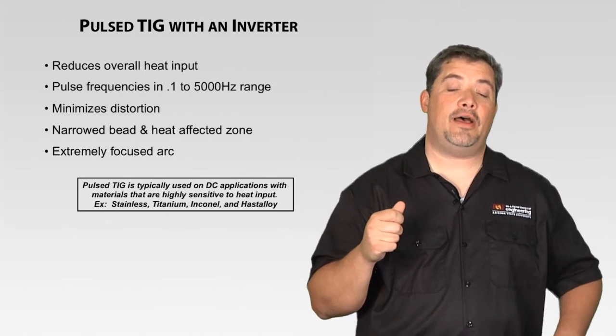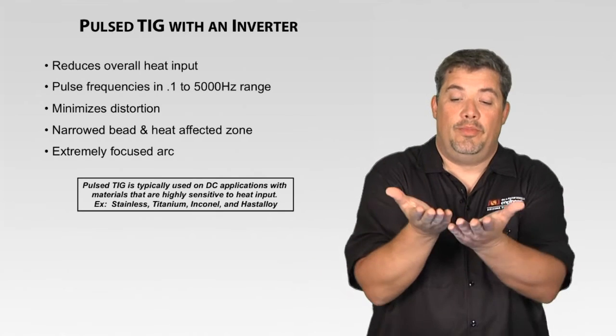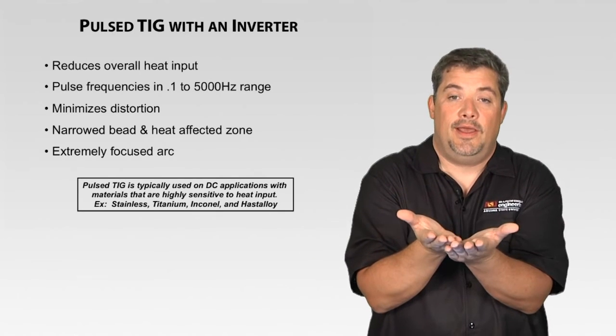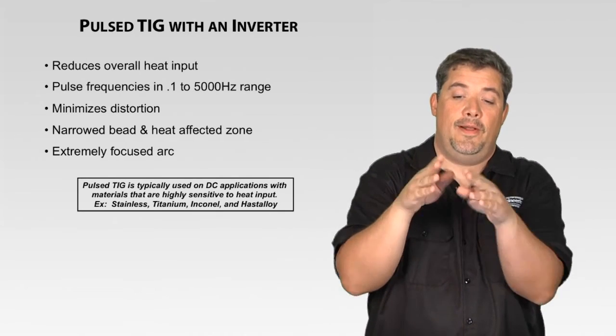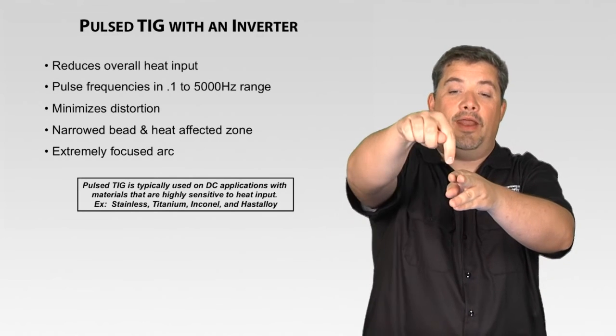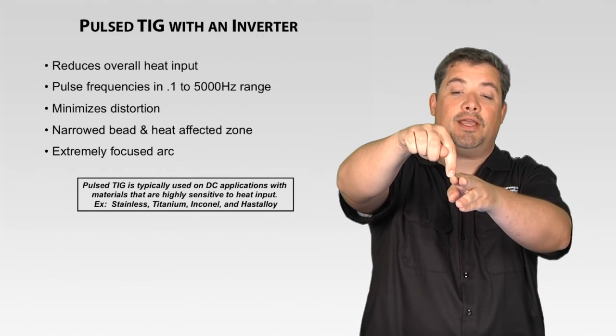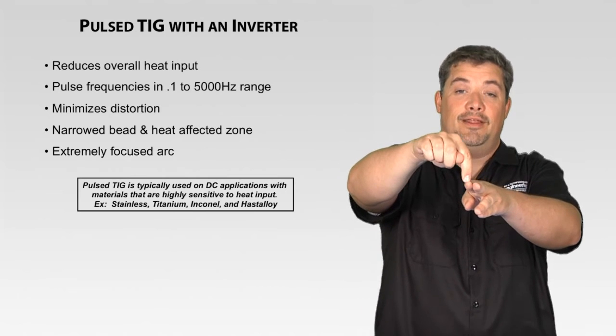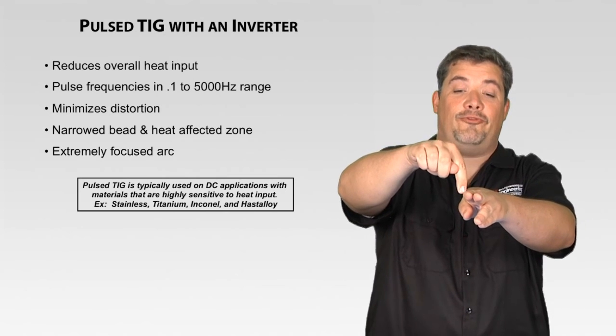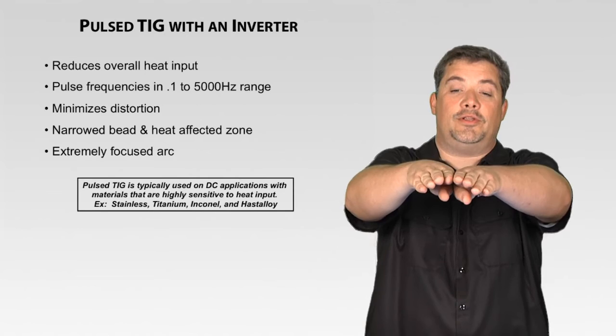Why would I go to 5,000 pulses per second? Well, a tube mill that takes flat sheet and turns it into a stainless steel tube, they actually just roll it out, and they'll use a 5,000 pulse per second, 700 amp DC inverter TIG welder to fuse that edge when it gets forced together.